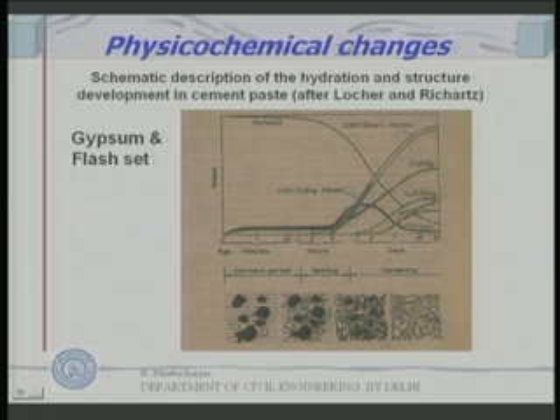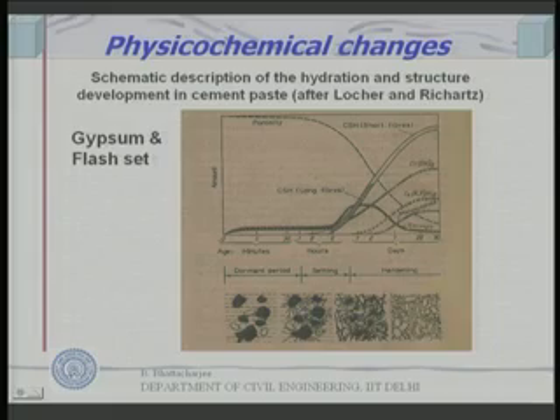Now, this ettringite formation essentially is required to control the setting. Ettringite is formed because of tricalcium aluminate reacting with the gypsum which we add. If we do not add gypsum, tricalcium aluminate will quickly react with water and it will give you the impression of flash set. So, that is why we add gypsum, and that controls the initial setting characteristics. Now, this ettringite expands in volume, and more ettringite formation from inside can burst out the coat that has formed on various materials, and further reaction of other material can proceed.